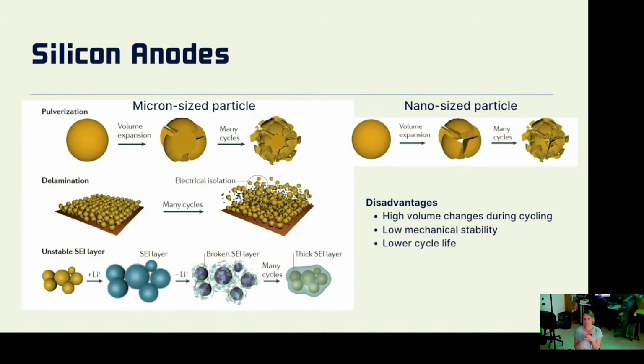Also, when it comes to the expansion and contraction of the particles, it can cause cracking, and the particles can actually break off and isolate themselves, they call it, so that they can't participate in the redox reactions. And it also can form a thick, what's called an SEI layer, or solid electrolyte interphase layer. And this is a coating of the electrolyte decomposition on the surface.